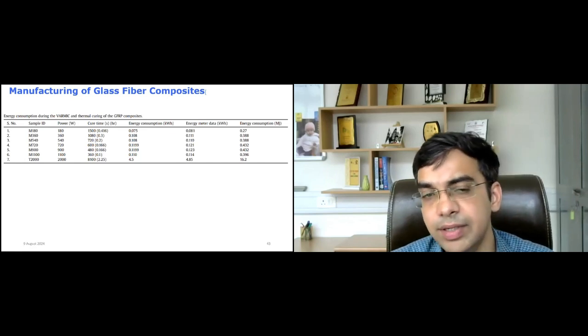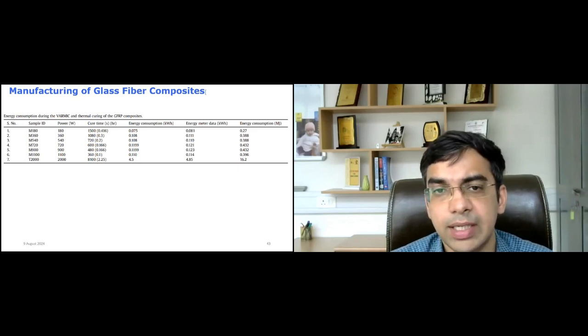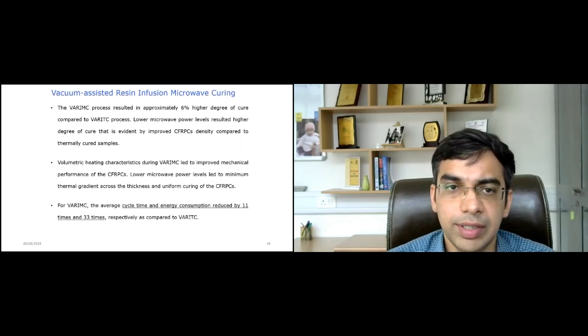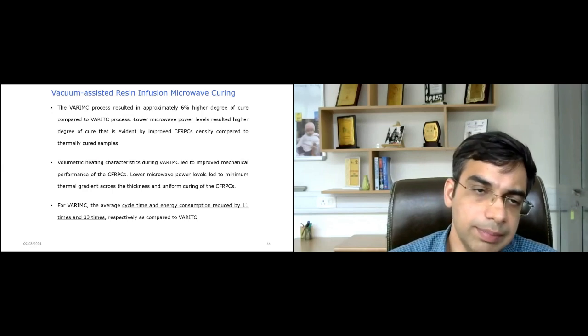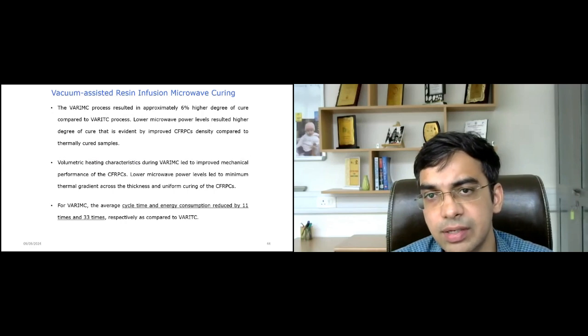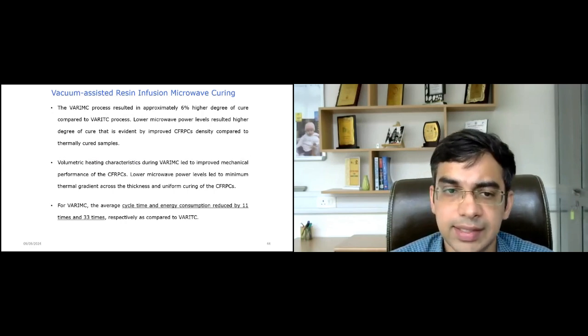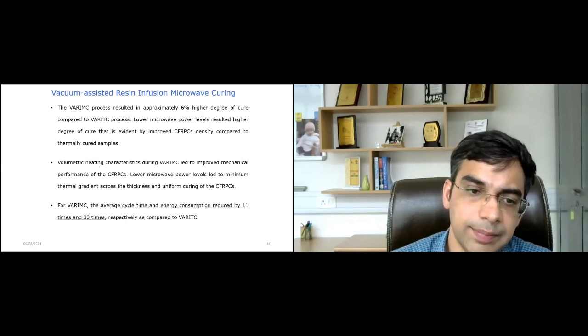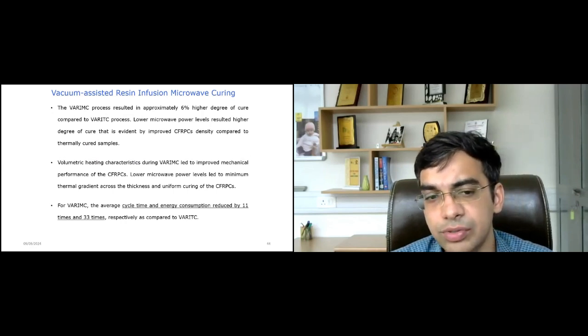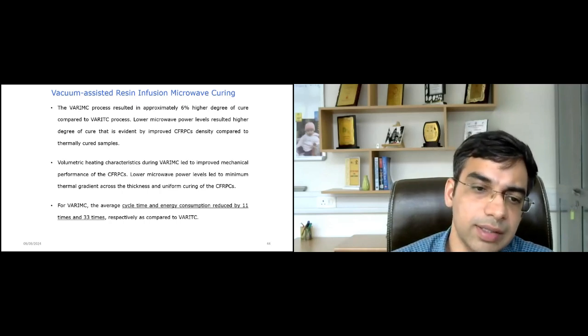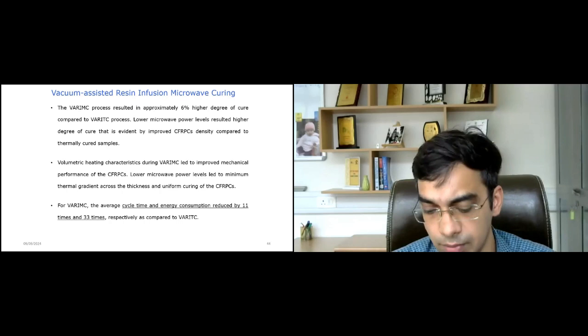But at the same time, we are generating composites with similar or maybe better mechanical properties. So the conclusion of the process that we have proposed, which we call vacuum assisted resin infusion microwave curing, has resulted in a higher degree of cure. At the same time, mechanical performance was better, and cycle time was also reduced by 11 times. Energy consumption was reduced by 33 times when we compared it with the thermal curing.